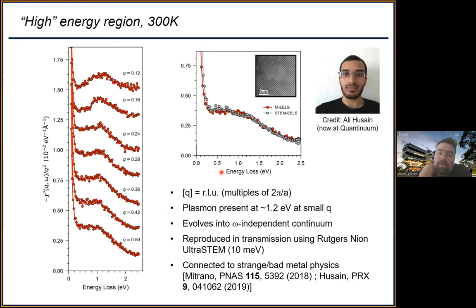Landau damping is a concept from the random phase approximation, from RPA. And I'm not sure if you're aware of this. If you calculate the lifetime of a plasmon in RPA at Q equals zero, it's always infinite. The plasmon is a delta function in RPA. And the reason is because RPA just allows for the possibility that a collective mode can decay into individual electron hole pairs. But in the real world, there are 4 body, 6 body, 8 body decay processes that are important that actually determine the lifetime of a plasmon. If you measure it in infrared, you know, there's a scattering rate. And to calculate a scattering rate requires really complicated many body physics, very hard to compute.